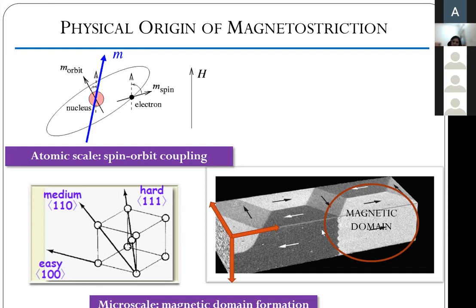So what happens is, when there is no magnetic field, the domains orient themselves along what's called the easy axis. For a material with cubic crystal symmetry, the easy axis is along 100, and it would take a lot more magnetic field to magnetize along other directions. If you see this triangular bracket, this means plus or minus 100, 010, 001, all possible directions. So that's what we see in this image, all 6 of these possibilities.